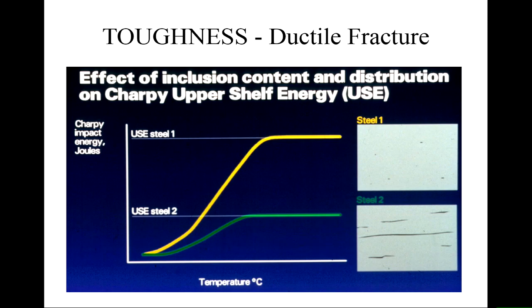Yep. So in steel 2, the image which you showed, that's the microscopic level, right? Right. Well, yeah. Those inclusions there are microns in size. So, in order to look at that, you would cut a piece of steel, you'd polish it to a mirror finish, and because there's a difference in reflectivity between the steel and the inclusion, you can see them in the mirror finished case. If you want to see the steel microstructure, you then chemically etch it, but you don't need to do that to see these inclusions. So yeah, these are very small. These are not big defects.